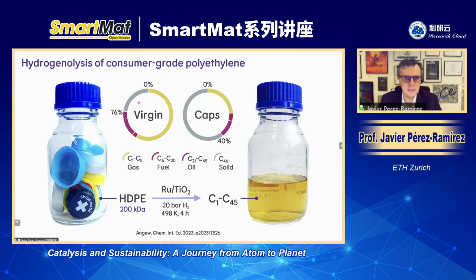And what this graph compares is that if you compare pure polyethylene with real polyethylene, so real caps from Coca-Cola bottles, the product distributions that you will get are very different. We get less gas, probably a similar yield of fuel and oil fractions, and more solids. And that's because of all the additives that exist in real plastics, which will need to be taken into account in the design of catalysts, because pure plastics are a nice way to start research, but not representative, because every plastic has multiple additives which will play a role in the catalytic function.